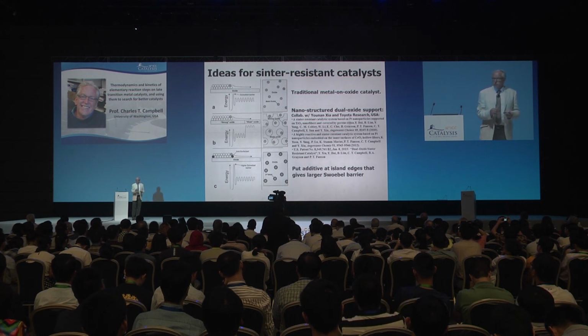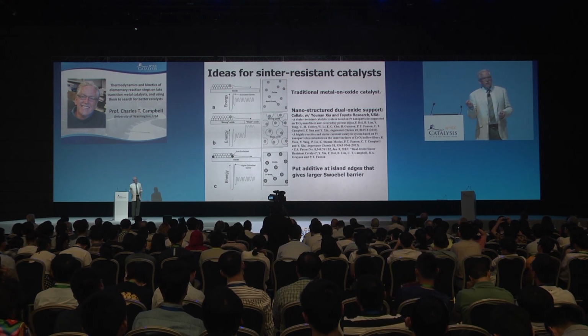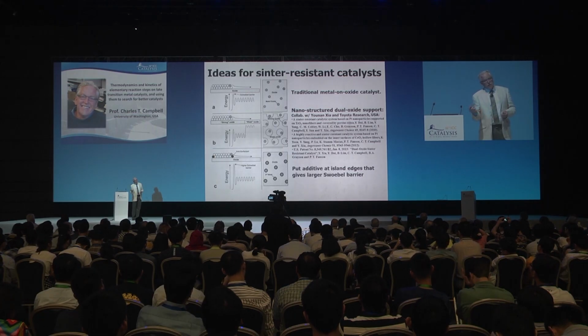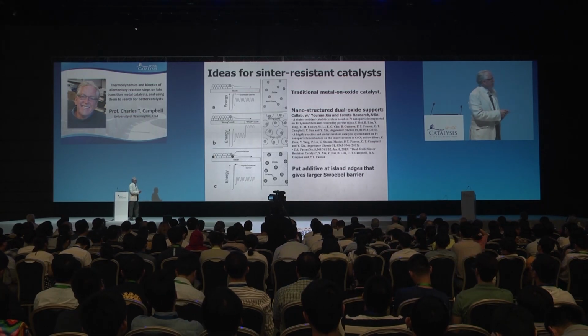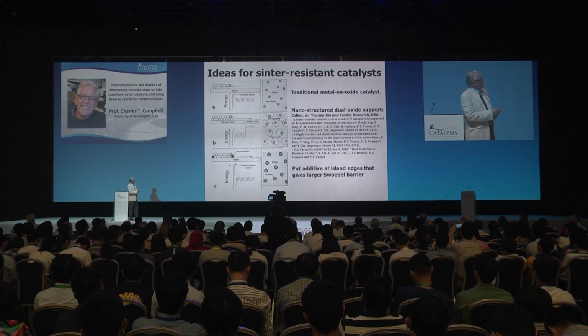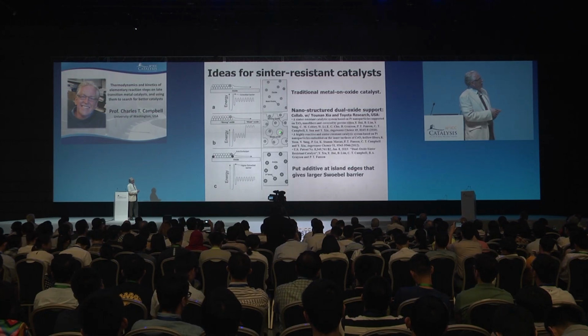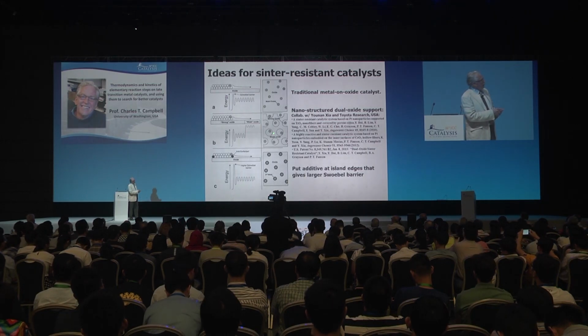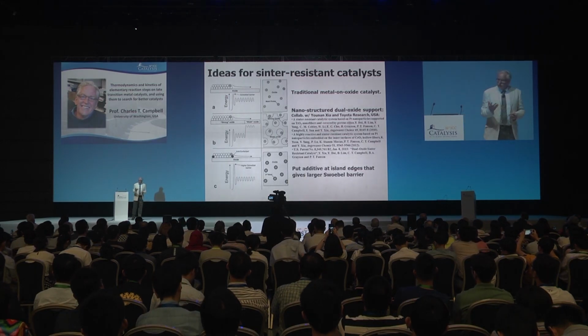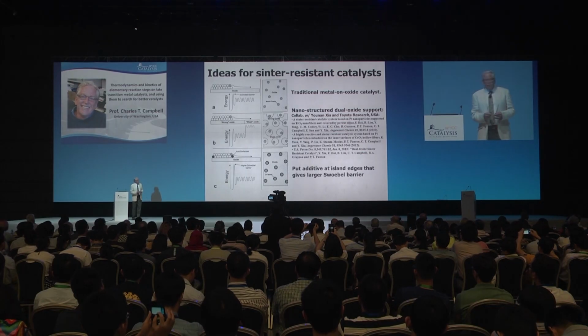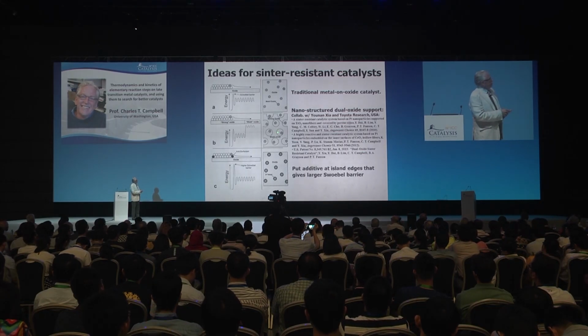By weak and strong, I mean an oxide that binds the metals weakly and one that binds the metals strongly. And if you think through the kinetics of sintering on such a surface, if you can make a catalyst where you only have one metal cluster per domain of strong oxide, the rate of sintering should be slower. In fact, that turns out to be the case.